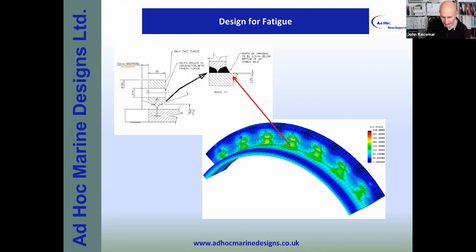And on top of that, we decided to just here do a little undercut of the toe of the weld. I looked at many research papers and they're all suggesting to me the same thing. If you can undercut the toe of the weld, you can improve your fatigue life. So that's what we did around the entire circumference of the jet duct and also on the transom itself, because the transom was only 6mm plate. It was just a diaphragm. It was flexing.